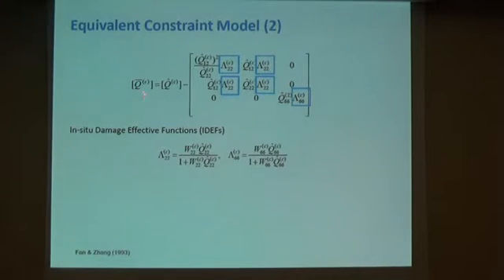The stiffness matrix of the cracked ceramic layer can be represented in this form. Q hat is the stiffness matrix of the undamaged ceramic layer, and the matrix that is subtracted from it contains stiffness properties of the ceramic material, and these two functions, lambda 22 and lambda 66. They are called in situ damage effective functions. They account for damage in an effective manner, and in situ refers to the fact that they take into account that the layer with cracks is situated between two other layers.